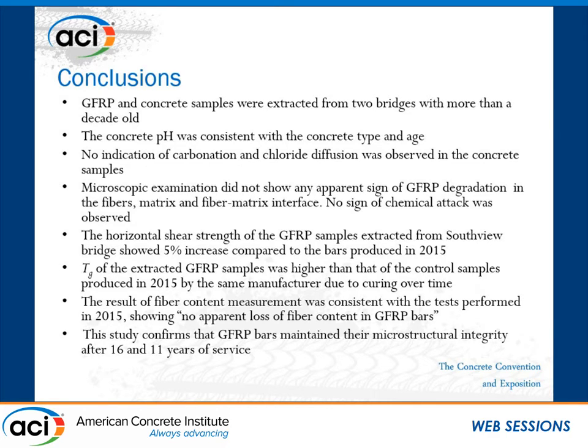So the main message of our study is that GFRP is a durable material, and this study shows that after years of service, basically nothing has happened to this material, and specifically for structures which are exposed to aggressive environments, as I mentioned, such as marine structures, bridges, seawalls. This could be a perfect and effective solution for removing the corrosion problem of steel rebars.